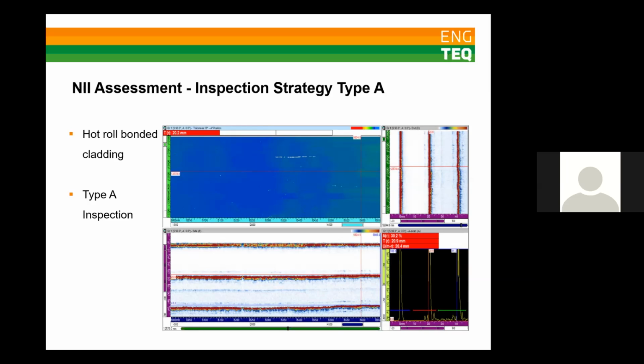So this results in a plate with a fine grain structure in both the substrate and the cladding. This means that angle beam shear waves can often be used for detection of stress corrosion cracking in the vessel shell or the cladding layer. So inspection techniques should be sensitive to low-level degradation in the corrosion-resistant alloy clad layer. And so typically we would be doing a 0 degree method for wall thickness along with an angle beam UT method for signs of cracking.